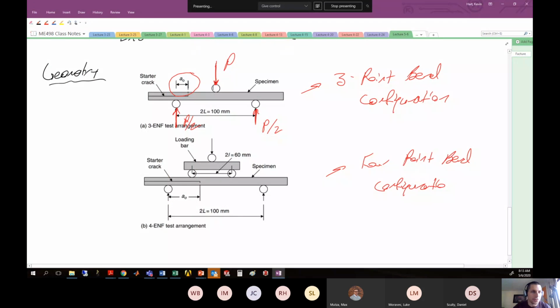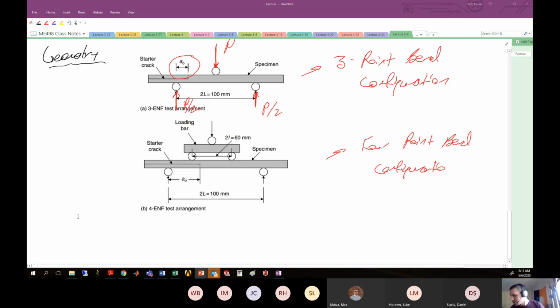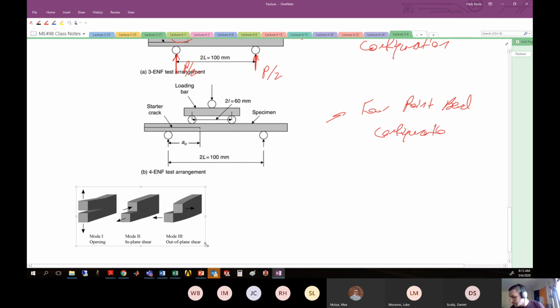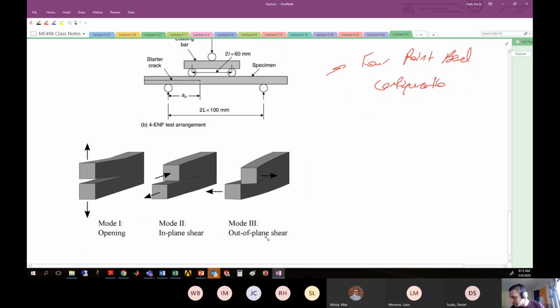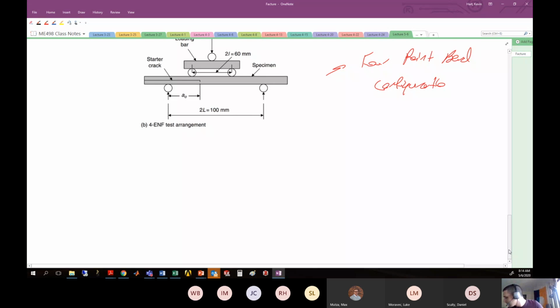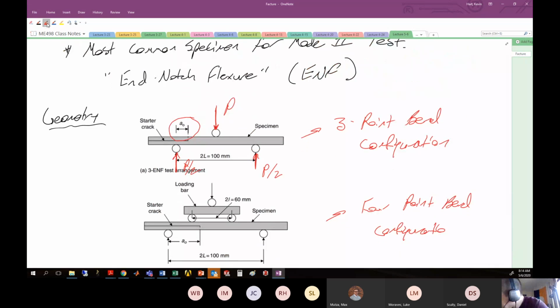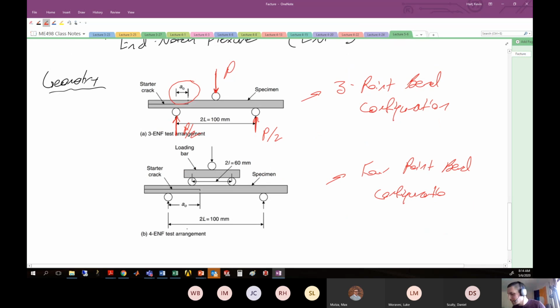So remember that our mode 2 looks something like this. I'll bring in the picture just to remind you of our different failure modes. So here's the mode 2. I'm going to take this away in just a second, so don't worry about copying this down. But here is this mode 2. All right, and it's like sliding against each other. That's what we're trying to achieve by putting this into bending, getting those layers to slide against each other in shear. So that's what's happening with this end notch flexure sample. Right at the midplane here, these guys are trying to slide against each other like this. That's that shearing type failure.